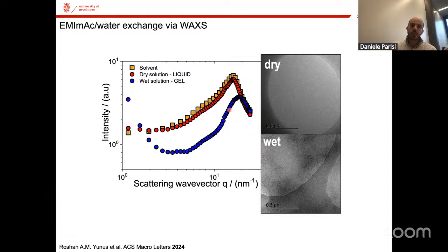What we can see from here is something similar to what we witnessed with the Raman spectroscopy: as soon as you add water, this peak here shifts towards larger, let's say, scattering wave vectors or smaller length scales, again suggesting that we are replacing the cation with a much smaller molecule, which is basically water molecules. Some cryo-TEM experiments also show that in dry conditions, everything is very homogeneous. We could not see anything, but in the wet state, you start seeing a very big spot, most probably hinting at some big clusters of cellulose and water.